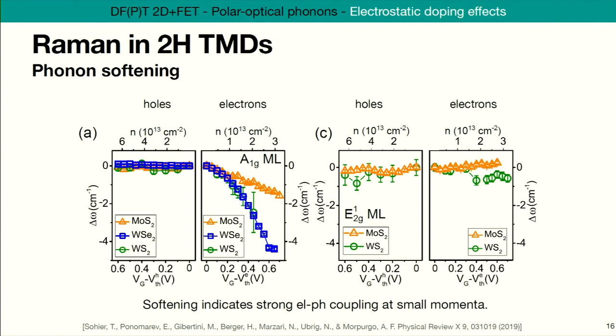Okay, now they look at the position of the peak, that is the frequency of the phonon as a function of doping. In particular, they look at how it changes. They do this for holes, so they put holes in the valence band, and then they put electrons in the conduction band, and they look at both changes in the frequency. So most of the time, it doesn't change. So the frequency of the phonon stays the same, except for this A1G mode, so that's the change in thickness.